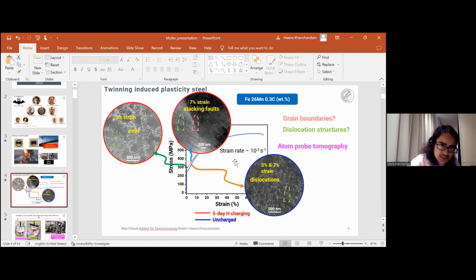Second, mostly in this material, we have these screw dislocations which do not have the hydrostatic field where hydrogen likes to sit. So in most of the studies where they have shown hydrogen segregation at dislocations, mostly they're on edge dislocations, because edge dislocations have this hydrostatic field and hydrogen segregates at them.